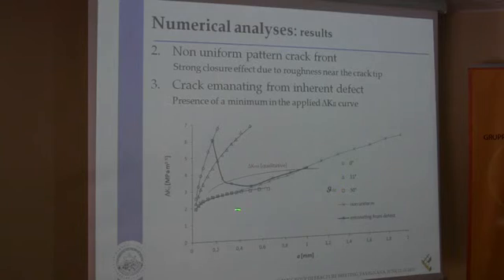We note that the non-uniform pattern crack front is overlapped to the curve referring to the slope of 30 degrees for short crack length, because this is the slope experimentally present near the crack tip. But also for longer cracks, the curve remains quite low, which means that the closure effect is mainly due to the roughness near the crack tip.